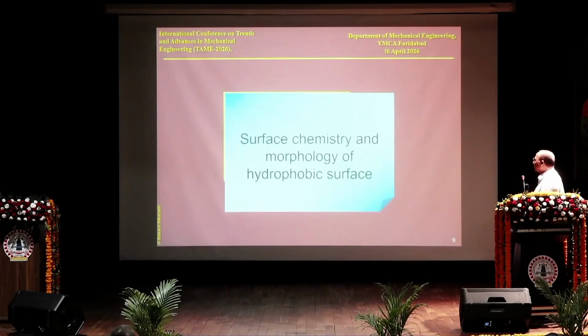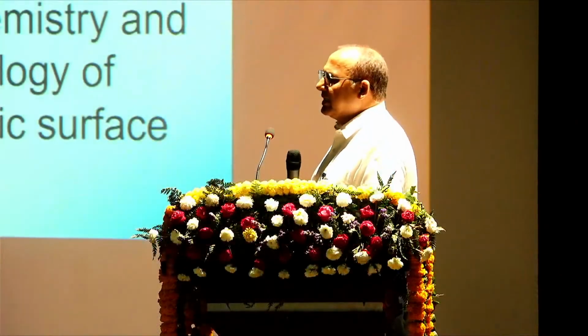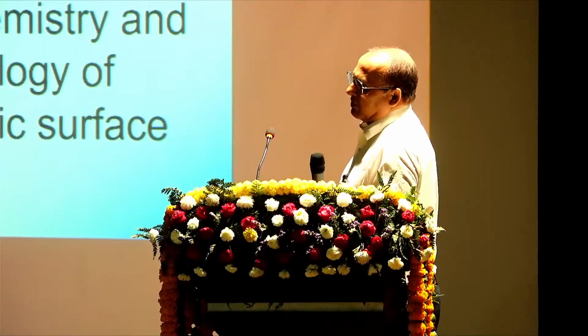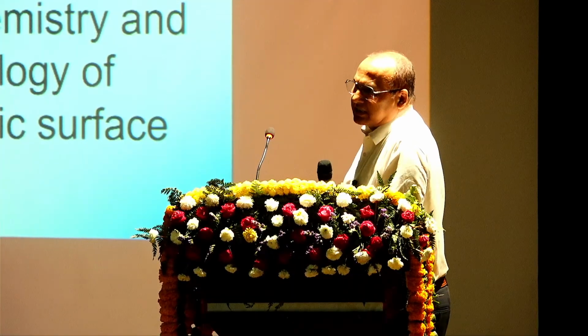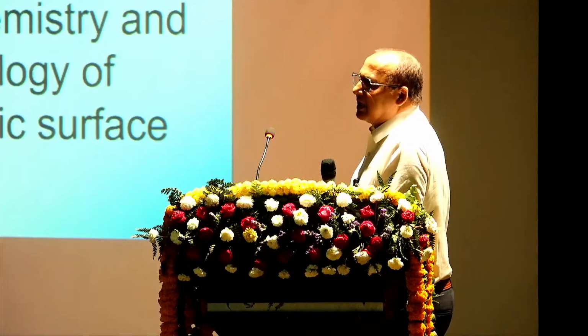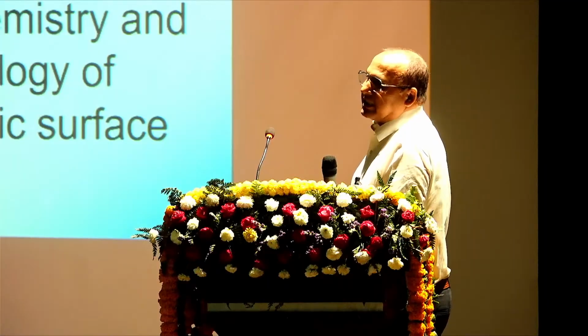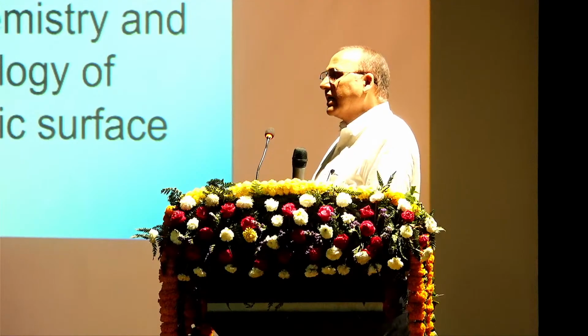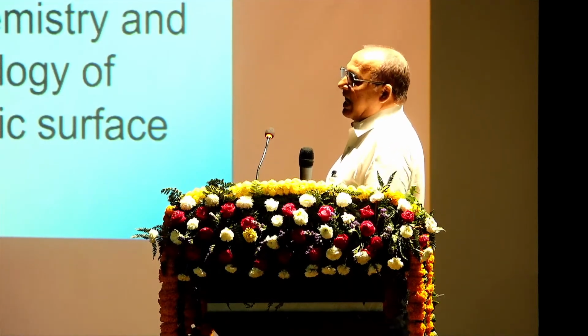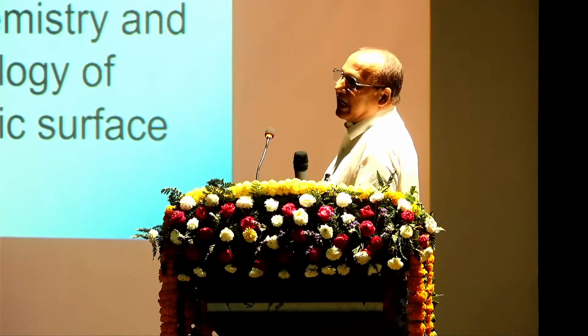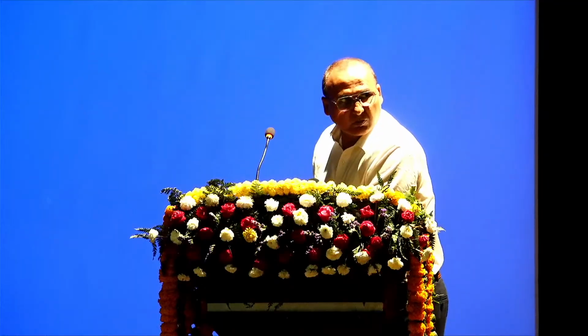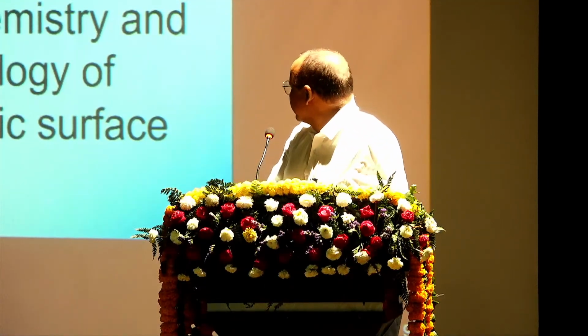Next slide. For drop-wise condensation, we need a hydrophobic surface, ideally a super hydrophobic surface with low contact angle hysteresis. That is one important thing. In nature, most metallic surfaces, like copper and aluminum, are hydrophilic. They are high energy materials. So we have to alter the morphology of this surface. Next slide.